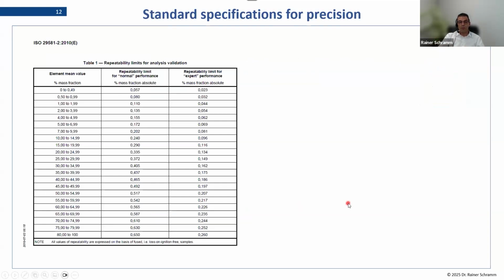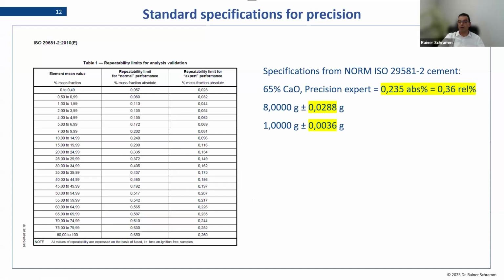If we look in some standard norms, like the cement norm, they also mention what is the performance you should achieve, so that for a certain concentration you know what is the precision you should have. And this means this is the maximum error which is allowed in our method. So of course, all our weighing errors should be below that. Otherwise, we cannot achieve this performance. Here you see that if I have a cement with 65% calcium oxide, then I should achieve something like an error of 0.235%. And if I convert this again to weighing a 1 gram sample, it would allow something like 4 milligram error, and it would allow already 29 milligram on the flux weight. That means this is exactly the error which is still in agreement with the method used.